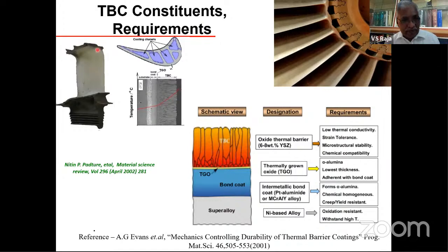These are all the turbine blades that we talk about, gas turbine blades, and this is coated with an oxide coating. There's a thermal mismatch between this metal and oxide coatings. In order to reduce the thermal strains, you have a bond coat, which has a coefficient of thermal expansion that lies between the oxide coating and the metal, and this gives you a nice graded performance from the point of view of thermal expansion. Now, the point here is when you cycle the temperatures and there is going to be strain involved in these coatings, that means the strain has to be tolerated. How do you tolerate the strain? You tolerate the strain by growing these oxides in a columnar manner. Please look at this. There is aligned growth of these oxides.